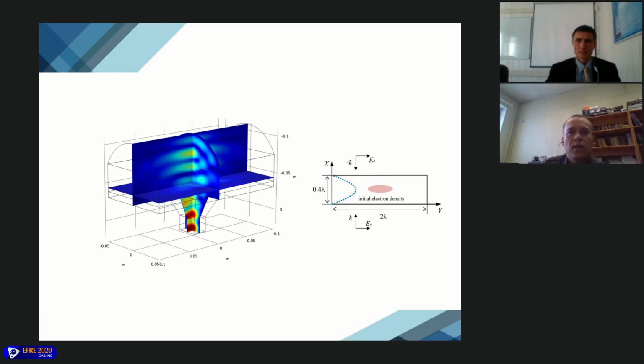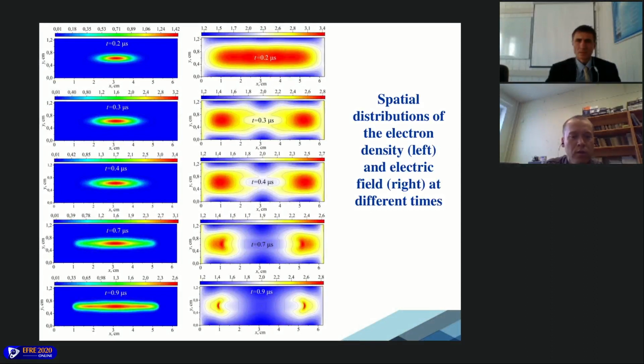In this formulation, only one anti-node is formed in the computational domain in the standing wave. Despite the fact that this formulation of the problem is to some extent a model, it allows one to study the dynamic properties of a single microwave plasmoid stretching along the electric component of the microwave electric field. Here we can see some results for the initial conditions. Here we can see contours of electron density, and here we can see the electric field.